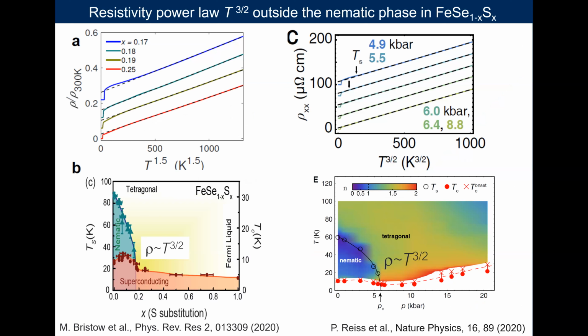Now, resistivity outside the nematic phase seems to have a power law of 3/2, both when we tune with chemical pressure and applied pressure. And this again needs to be understood, where it originates. Is it again evidence for the acoustic phonon coupling or some other reasons?